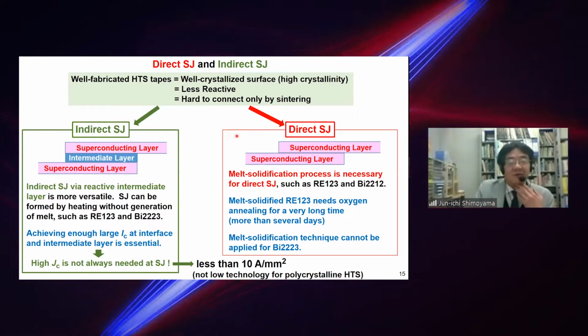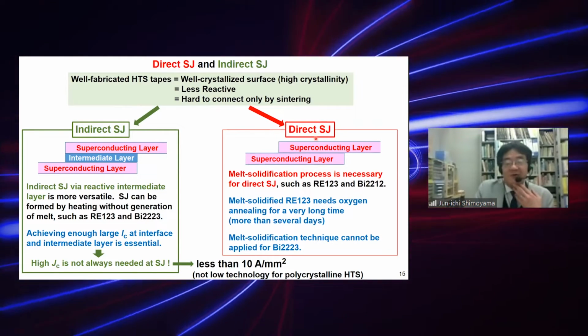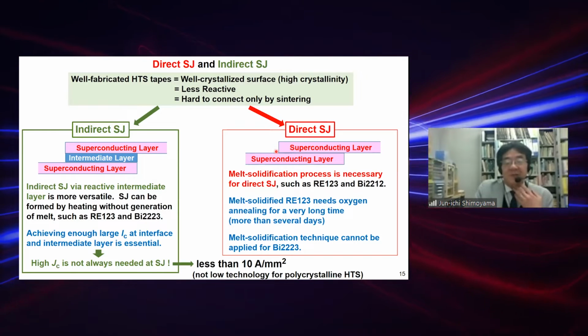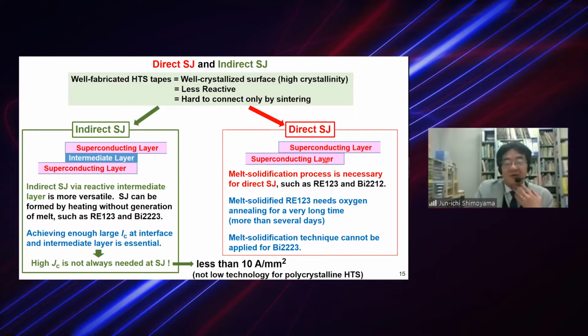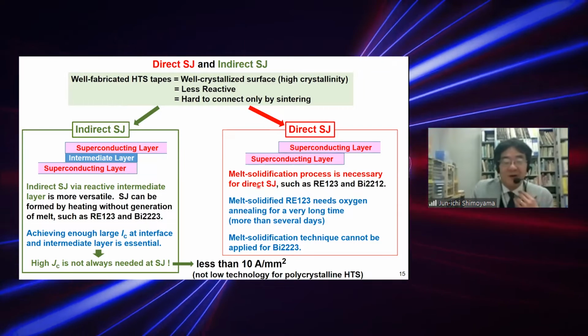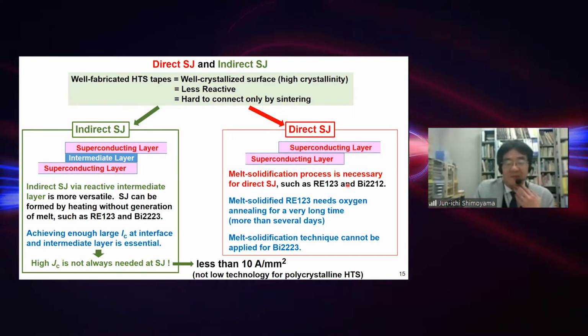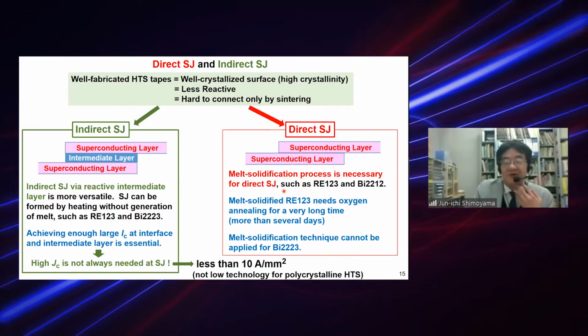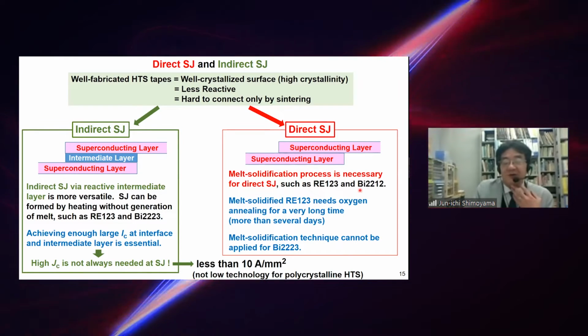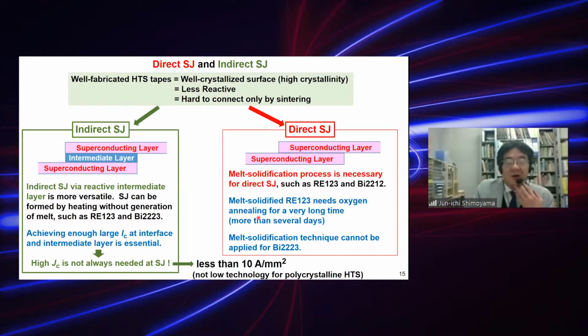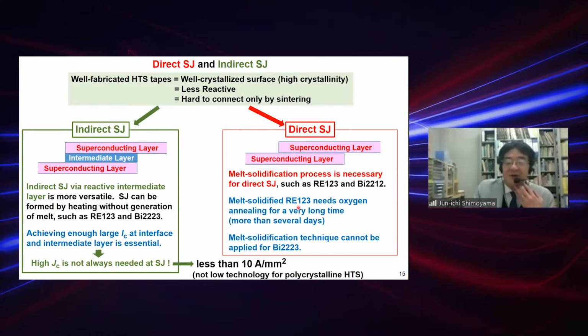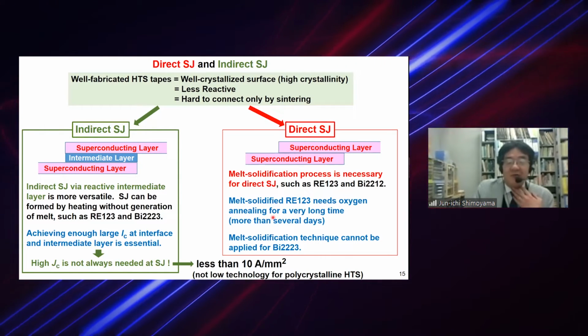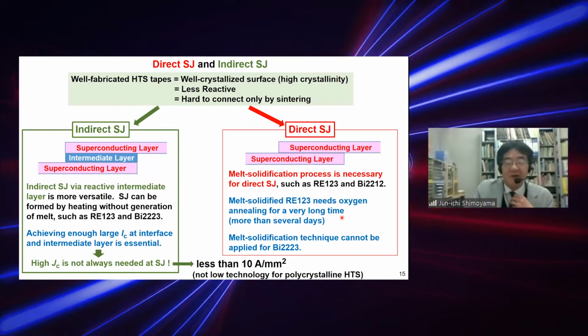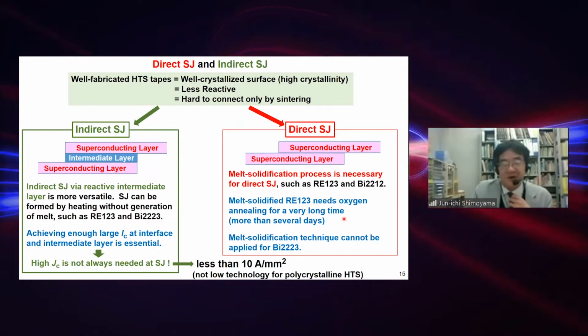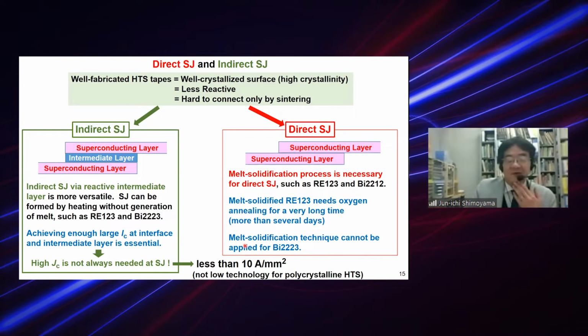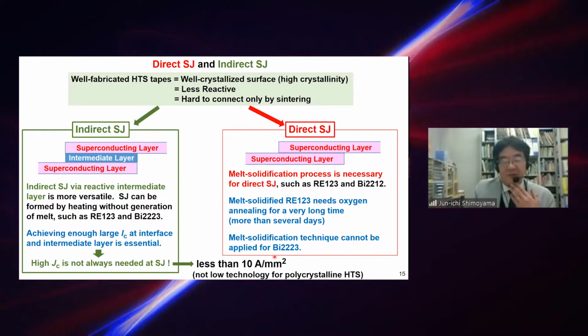In the case of the direct superconducting joint, you see the superconducting layer connected directly in this way. A melt solidification process is necessary for a direct superconducting joint, such as RE123 and bismuth 2212. However, melt solidified RE123 needs oxygen annealing for a very, very long time because of the very long diffusion path for oxygen. And the melt solidification technique cannot be applied for bismuth 2223.